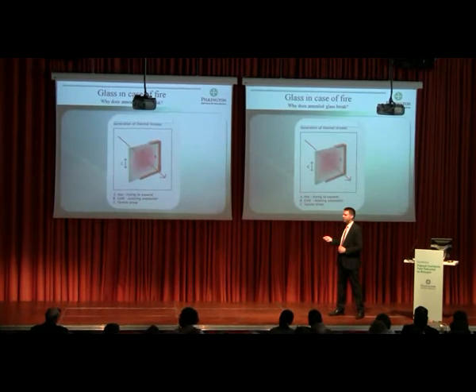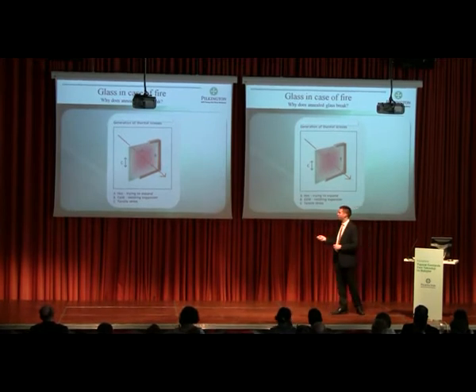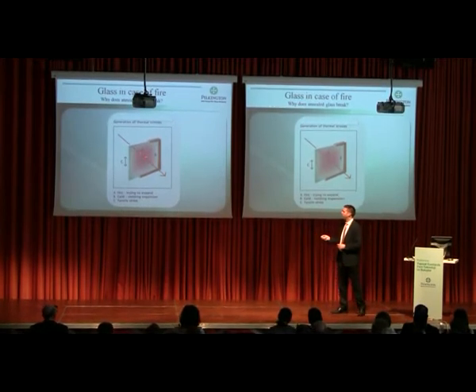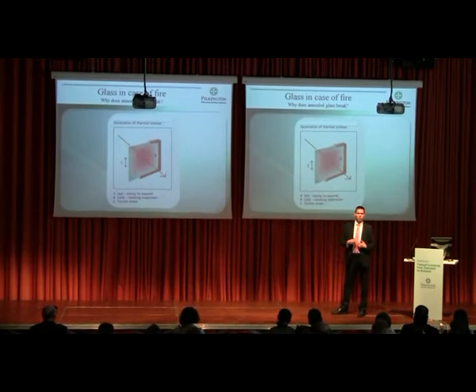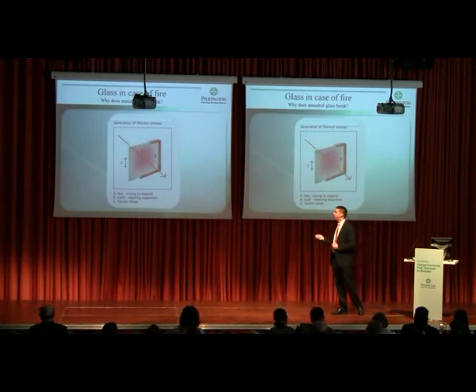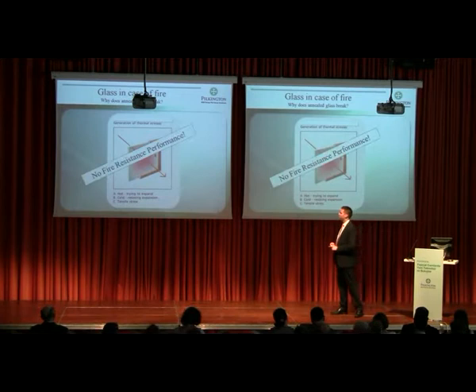So we're saying that if there is a temperature difference from here to here of approximately 40 degrees, so that means you have 20 degrees here, 60 degrees in here, then normal annealed glass will get some cracks and then totally collapse in case of fire. So although it is a non-inflammable product, annealed glass is not able to withstand any fire. So no fire resistance performance for normal annealed glass. That is the reason why we produce fire protection glass.